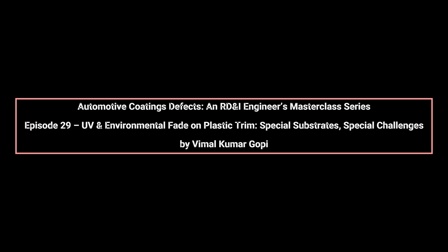Thermal expansion mismatch between the plastic substrate and coating amplifies stress. On hot days, plastic trim can reach temperatures significantly higher than painted metal panels. Expansion and contraction cycles create microstrains that promote crazing, microcracking, and surface roughness. These microstructural changes scatter light and reduce color vibrancy, which is perceived by the customer as fading. Edge and corner regions, especially around mirrors, grills, and body side moldings, are most vulnerable due to geometric stress concentration.